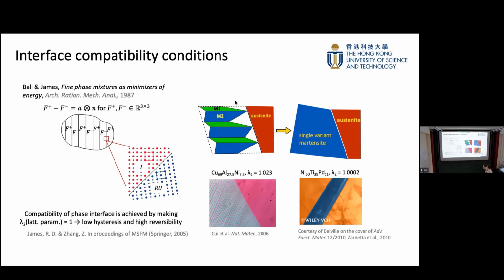And people also observe it in some very special nickel titanium doped with palladium, a very delicate doping element that can exactly make the lattice parameters right, so that this kind of atomically sharp interface exists. And then people find that when we make this kind of geometry happen, the real material shows very low thermal hysteresis, and the material becomes highly reversible in terms of thermal cycles.